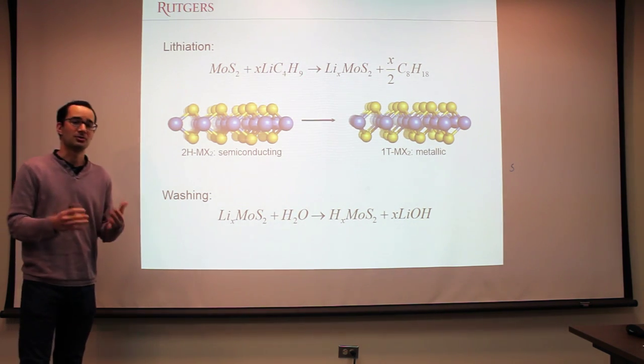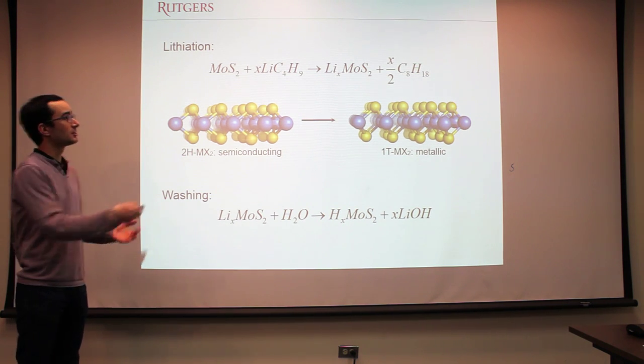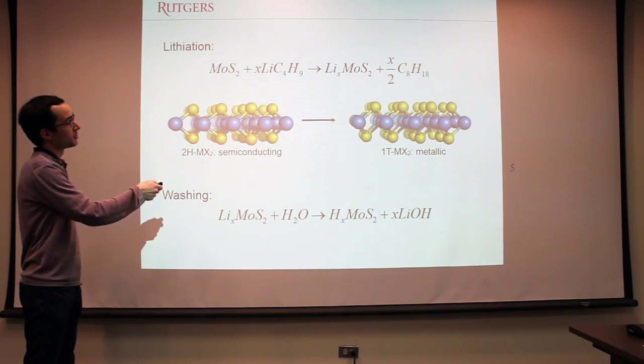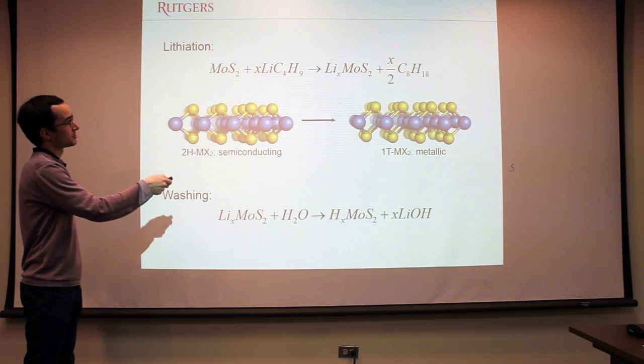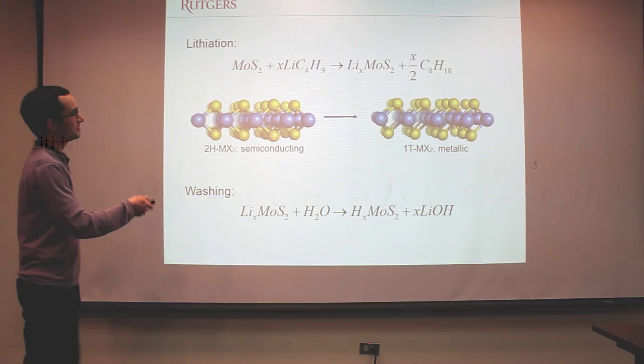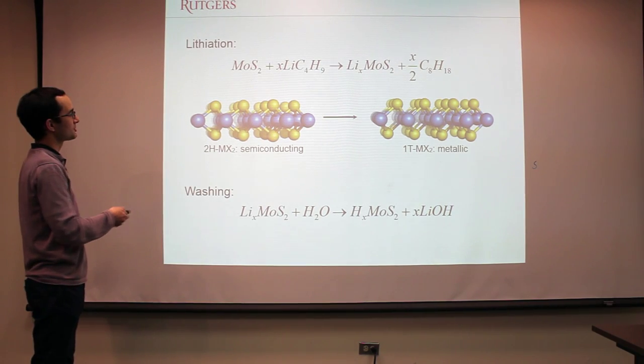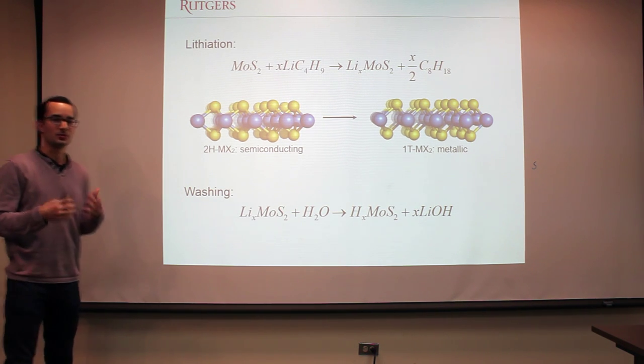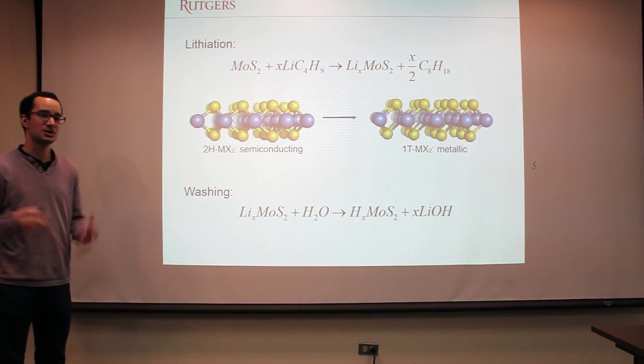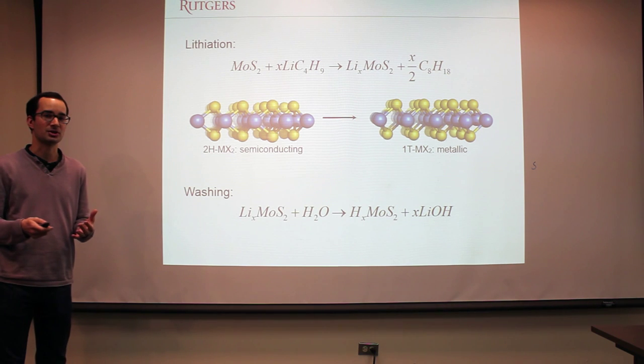After a certain desired amount of time, we stop the reaction and wash with hexane. When we wash, we end up with lithiated MoS2 and we can remove the byproduct using hexane. During this lithiation step, we start with flakes of MoS2 that have the 2H structure, which is known to be semiconducting.